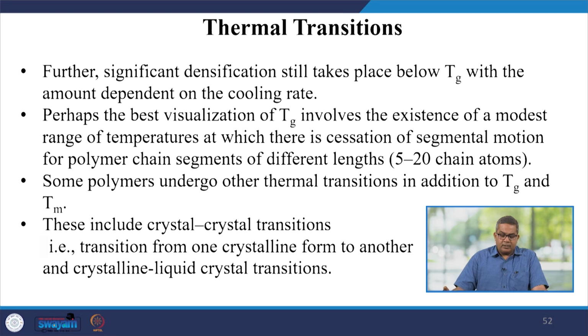Now, significant densification still takes place below the glass transition temperature, where the amount is dependent on the cooling rate. So, the best visualization of glass transition involves the existence of a modest range of temperature at which there is a cessation of the segmental motions of different polymeric chains.